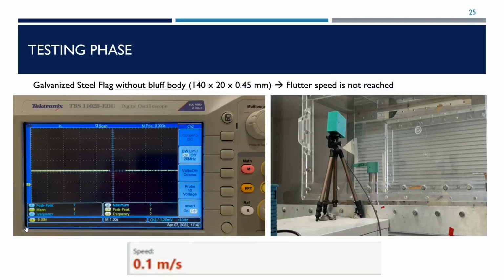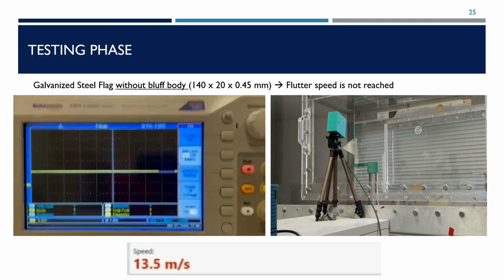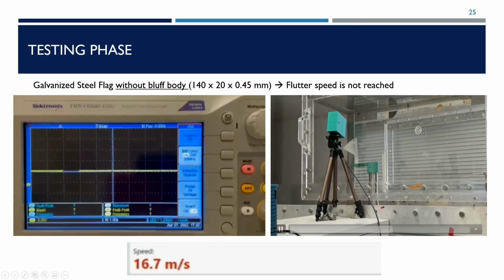Our first test uses a galvanized steel flag without a bluff body, and it has the following dimensions: 140 millimeters high, 20 millimeters wide, and 0.45 millimeters thick. Our experiment concluded that we could not reach the flutter speed of the flag.